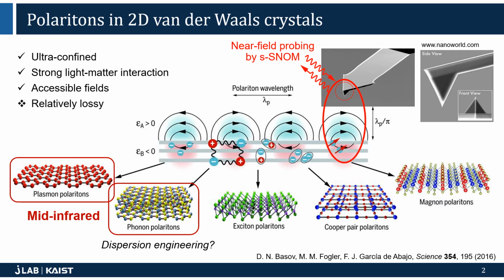The concept of Polaritonic Fourier crystal was developed to address a problem of polaritonic dispersion engineering in thin van der Waals crystals. Polaritons are quasi-particles born out of coupling between free space photons and collective oscillations of charges in the material. Specifically, the low-dimensional polaritons in thin van der Waals crystals are strongly confined and thus are able to provide strong light-matter interaction. At the same time, their evanescent fields penetrate beyond the material boundaries and are exposed to external